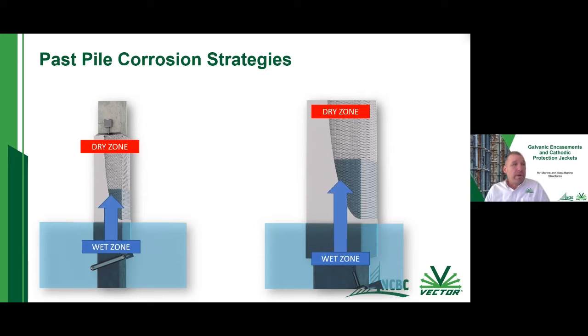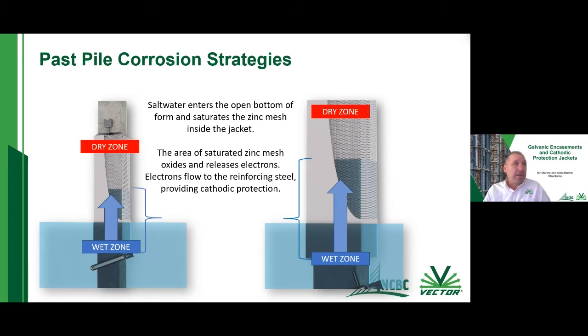So we have our wet zone, we have our underwater zone, and what ends up happening is some of the water enters the bottom of this jacket, and this salt water is going to saturate the zinc mesh and activate it, and provide corrosion protection, or cathodic protection, to our reinforcing steel within this jacketed area. So one thing to note is that only the areas where the salt water has entered the bottom of the jacket are going to get cathodic protection. As you start moving up higher and higher into the dry zone, the salt water is not available anymore.